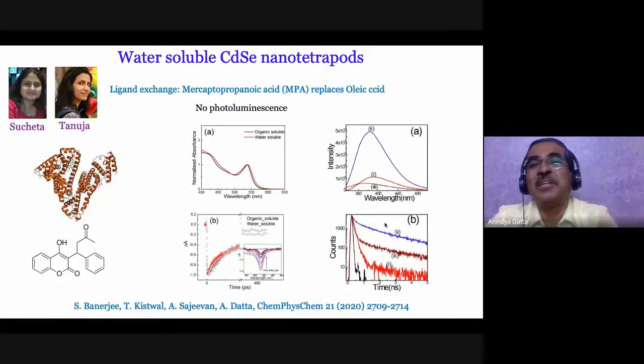Now, since we want to get to the bio-nano interface, obviously we need tetrapods that are water soluble. The tetrapods that I talked about so far are all soluble in organic solvents. That is because, see, all nanocrystals are covered with some molecule or the other. It can be a polymer, it can be a protein, it can be some small organic molecule. The original capping agent was oleic acid, which does not really want to mix with water. So we did something called ligand exchange, by which we could replace oleic acid by mercaptopropanoic acid, MPA, which is much more hydrophilic, and we were successful in preparing quantum dots, nanotetrapods that were soluble in water.